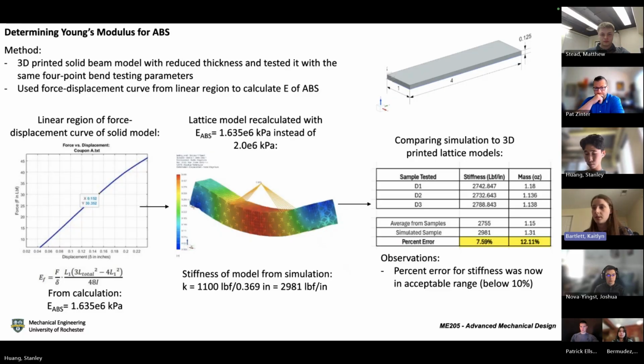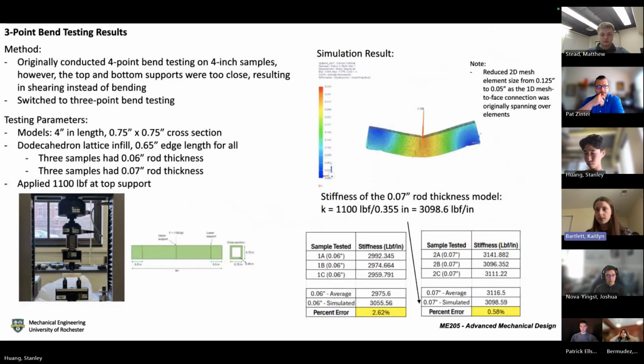And then after that, we moved to the 4-inch ones. We felt more confident in our results after we got the Young's modulus, and the results for the stiffness were much closer between the two. But then we moved to the 4-inch models, and this is what Angel was saying before. We originally tried the 4-point bend testing, but the top and bottom supports were really, really close, and it led to stiffness data that was very much wrong no matter what we did. That's due to shearing instead of an actual bending force applied. So then we switched to a 3-point bend testing setup, with all the same parameters.